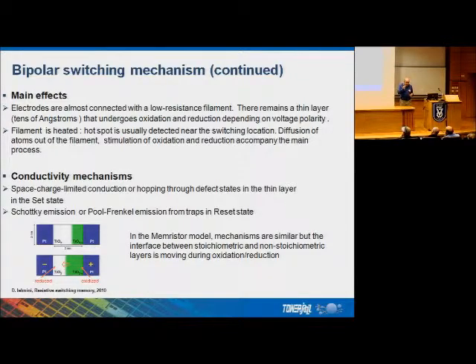And one of the main reasons is how do you make the measurements? Because the filament is formed by current which passes through the dielectric film, and there are abrupt changes of resistance, the capacitance of the structure and the capacitance of the load, the capacity of the cables which are used in the lab when the measurements are performed, have critical influence. So the higher the capacitance, the higher the charge that will flow into the leakage, into the filament. And the higher the current, the more advanced the filament will be. So during the forming procedure, the final resistance will depend significantly on the value of the current, on the value of the charge that passed through the system.